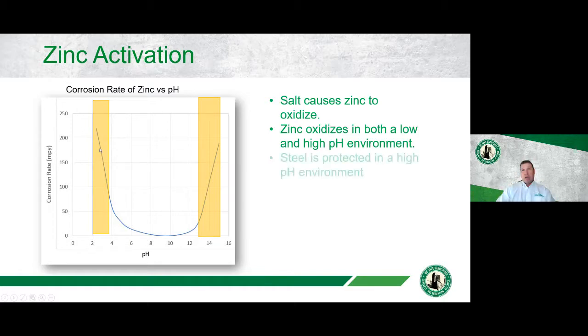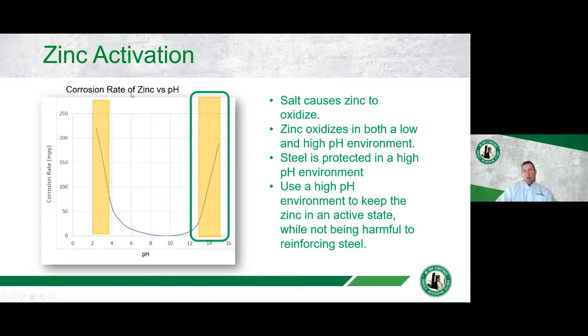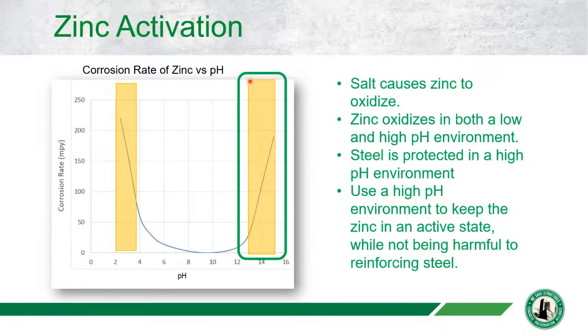So what we're going to do here is look at the table for the corrosion rate of zinc versus pH. Zinc is active in a lower pH range or a higher pH range. Steel is also protected in the higher pH range. Steel will not corrode. So we're going to use an environment of high pH so that it oxidizes our zinc, but at the same time is protective to our reinforcing steel. We could use a lower pH down here as well, but it would be aggressive to our reinforcing steel, oxidizing our reinforcing steel and the zinc at the same time. So it's much more beneficial to use a higher pH system here to activate our zinc or keep it in an active state.